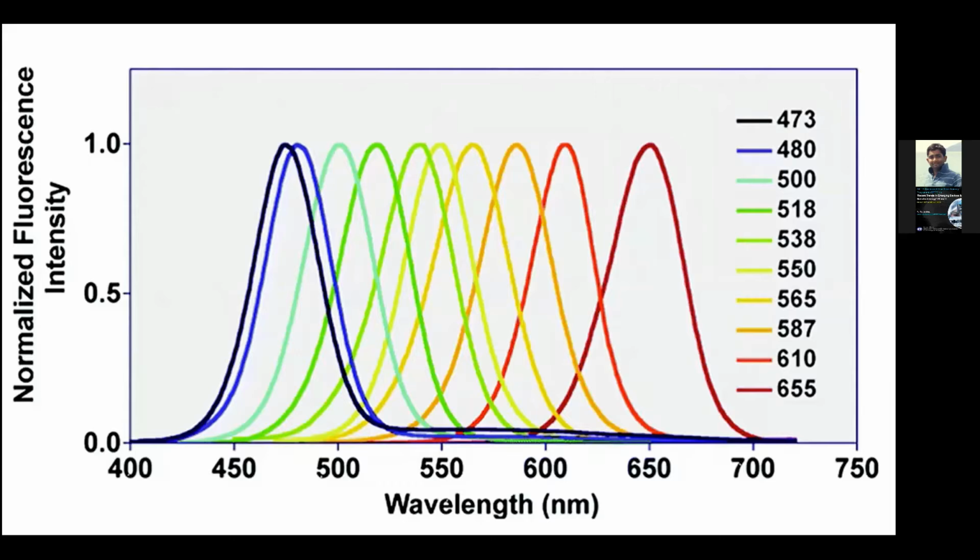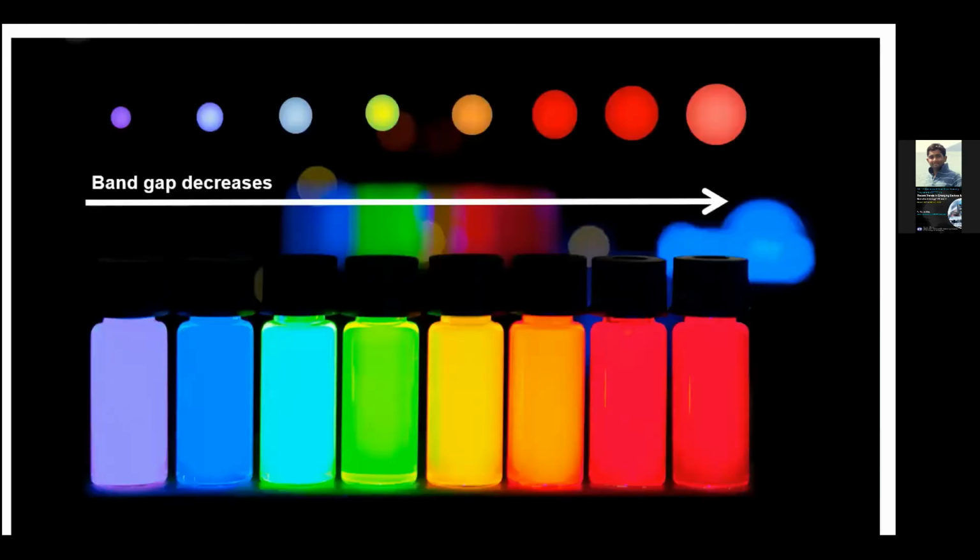Now, you can see that these are very bright. Many people say cadmium is very toxic. Yes, that's true, cadmium is toxic. But we have a solution to remove the toxicity. Generally, people coat the dots with zinc sulfide, so there is no cadmium leakage for the applications. And when you put on the zinc sulfide, it is also much more stable.